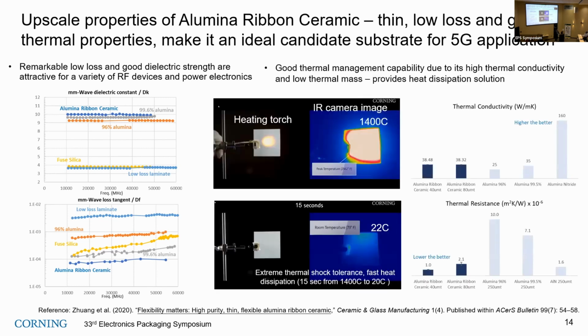It also has good thermal management capability, because we did a thermal shock test where we heated the substrate to 1400 degrees C, and within 15 seconds it cooled back down to room temperature. The thermal conductivity of this substrate with 40 micron alumina is around 38 watts per meter Kelvin.